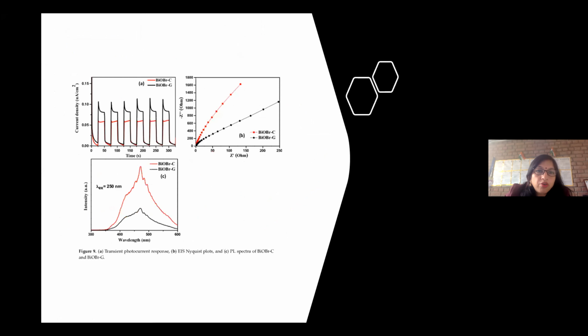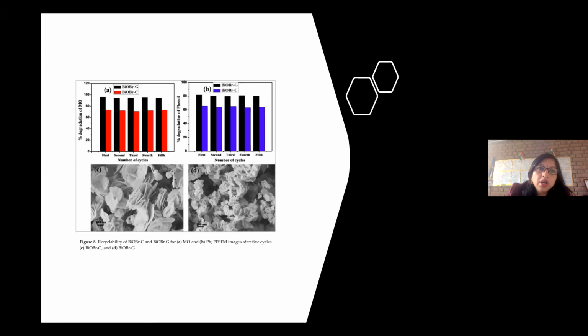And then the electrochemical studies were done: photocurrent response, EIS Nyquist plot, and photoluminescence spectra were taken. So in all cases, it proved that recombination of electron-hole pairs is less in the case of the green one. And recyclability studies were done to see if it can be used only once or many times. So we found that it can be used many times. After using it 5 times, SEM images were taken, and they were almost the same as earlier. So the material is safe and stable, and it can be used many times.